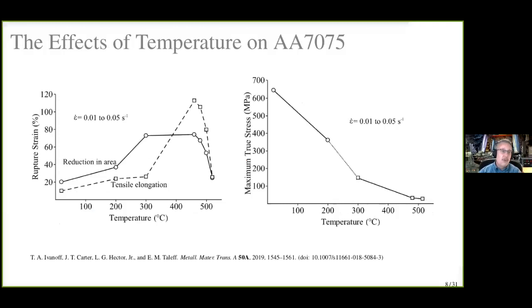So here's some nice work from my former student, Thomas Ivanoff. Here is rupture strain as a function of temperature for AA 7075. Now, all this material down here started in the T6 condition, just to let you know. So here we have room temperature. We're getting tensile elongations of 10 to 12%. We go up to 200 degrees Celsius, and what you see is that tensile elongation basically doubles right there. And our reduction in area basically doubles too.